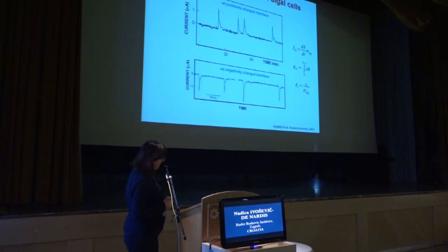What is interesting is that when we change the polarity of our applied potential, from positive going to negative, then we obtain reverse mirror images, which is proof really that our signal originates from the double layer charge displacement.